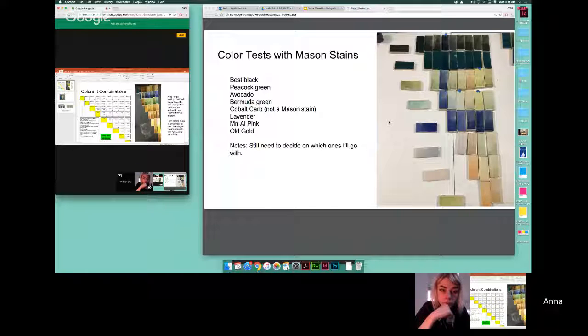We'll talk about this later when we do colorants themselves, but unless you go absolutely crazy, there are some colorants that will change as the percentages go higher. We just talked about copper: it will be turquoise at low percentages and an outright green at higher percentages. Iron goes through a huge variety of changes from low to high. It goes from a baby blue at very low percentages all the way to basically black, Tenmoku black, at 8 to 10%. And there's actually a green in there as well.